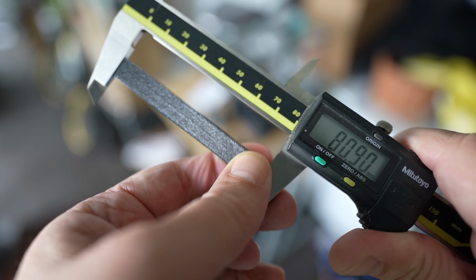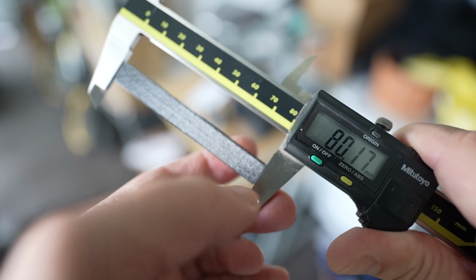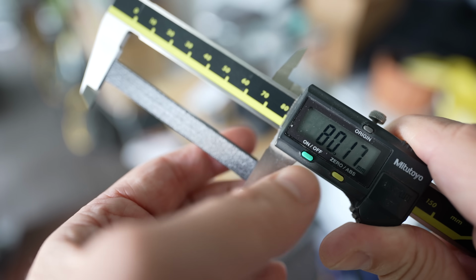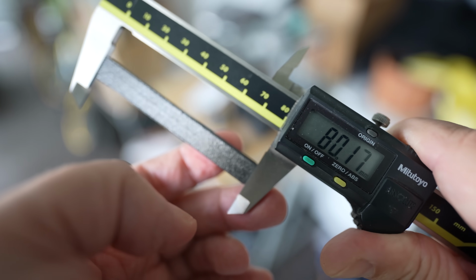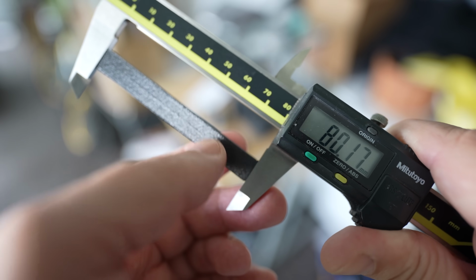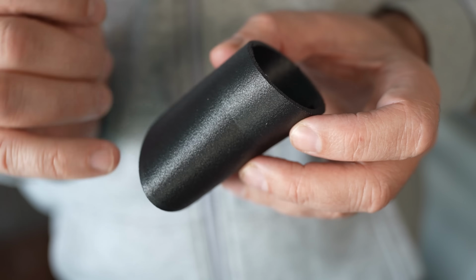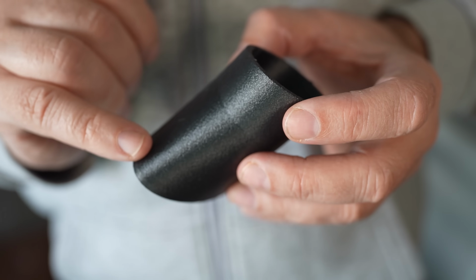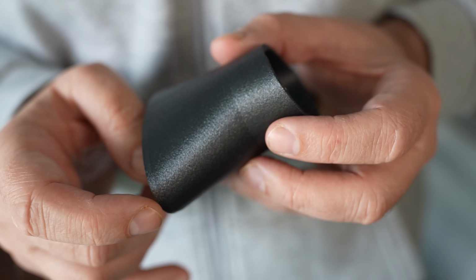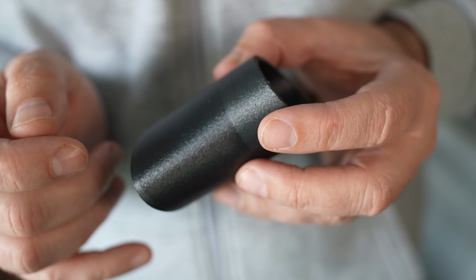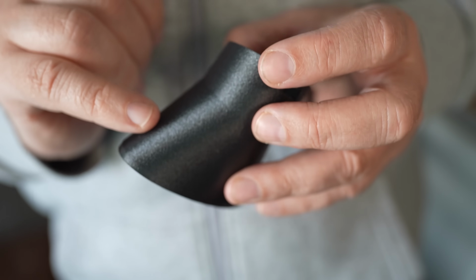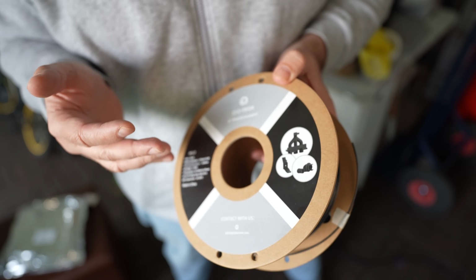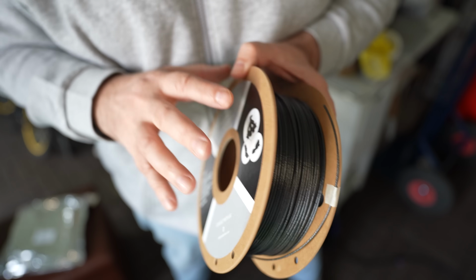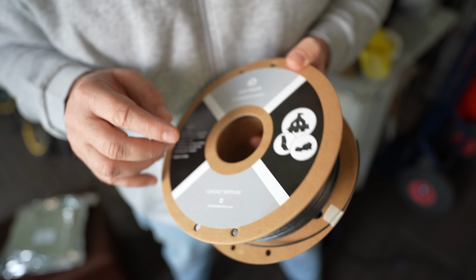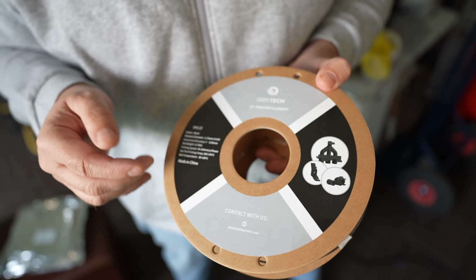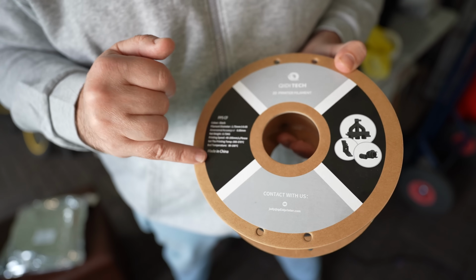I'm checking the shrinking, and actually there is no shrinking. I'm measuring above the elephant foot. It's even a little bit bigger, and this is a sign that I could dry it a little bit more, but it will be tested as it is. The reason for this are those micro water drops in the nozzle that will boil and push out a little bit more material. This is a good method to check if your filament is wet, but unfortunately only after the printing. That's why manufacturers should place this kind of filament on temperature resistant spools. Carbon spools are okay, but the question is only the glue which is used here, and this information should be provided on the sticker too.